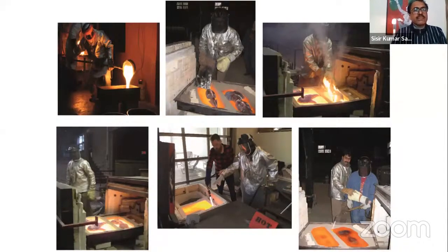And that tray, immediately after it gets a little solidified, around 650 degrees centigrade in outside temperature, can go into the kiln again when the kiln temperature is around 600 to 650 degrees centigrade. So here I am placing first pour clear glass onto the mold.